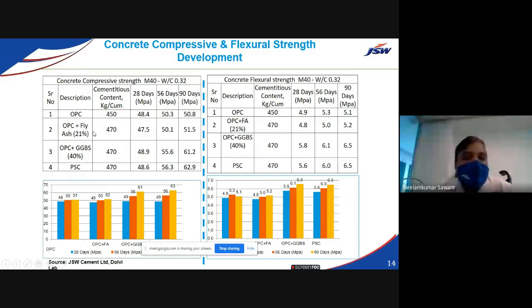If I am doing the combination of OPC by partial replacement of 21% with the fly ash, we can see at 28 days about less, 47.5 as compared to the pure OPC, and after 90 days it is 51.5. And if I am using replacement of OPC by 40% of GGBS, this strength is equal to whatever OPC, that is 48.9 MPa at the 28 days level, and after 56 days it is increased about 55.6, that is 4 to 5 MPa increase, and after 90 days also it is 61 MPa, means drastic 9 to 10 MPa is the additional strength I am getting if I am replacing OPC with